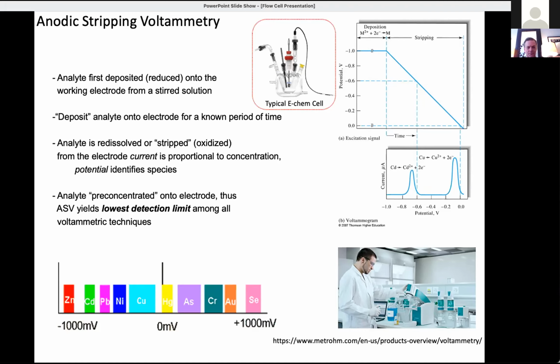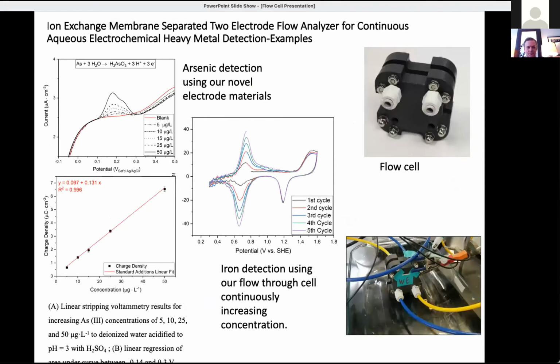Here's an illustration of a laboratory setup here. This is courtesy of Metrohm. They develop a lot of the benchtop and field analytical equipment, which uses anodic stripping technology. And again, it's a batch technique. And these are some of the ions and the potential ranges which they're stripped over. So you can see zinc, cadmium, lead, nickel, copper, mercury, arsenic, chromium, gold, which is rarely in your solution, or selenium, which are less likely.